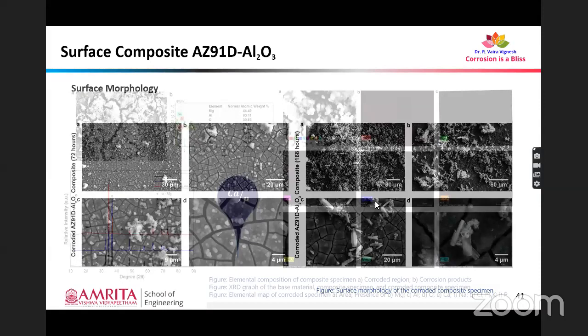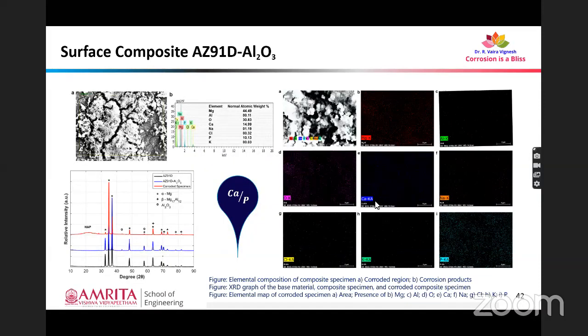Yes, coming towards analysis, we have done EDS and XRD analysis to confirm the presence of corrosion products and the composition of corrosion products too. So the initial analysis was EDS analysis. From this we came to a conclusion that the corrosion product consisted of magnesium, aluminum, oxygen, calcium, sodium, chlorine, potassium, and phosphorus. So these are the major elements in the corrosion products.